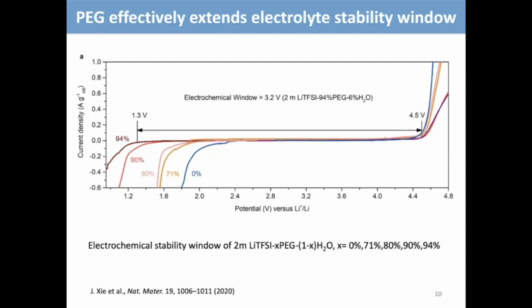First we conduct the LSV to see the electrochemical voltage window. As you can see here, the hydrogen evolution onset potential is significantly delayed as we increase the content of PEG from 70% all the way to 94%. And with 94% of PEG, we're able to delay the HER to after 1.3 volts versus lithium.